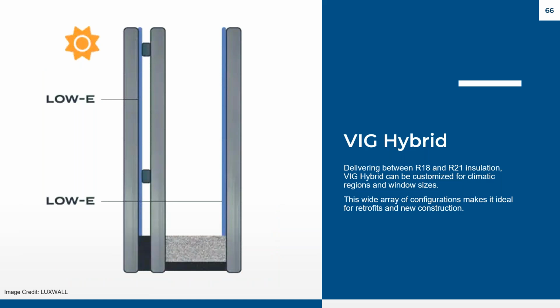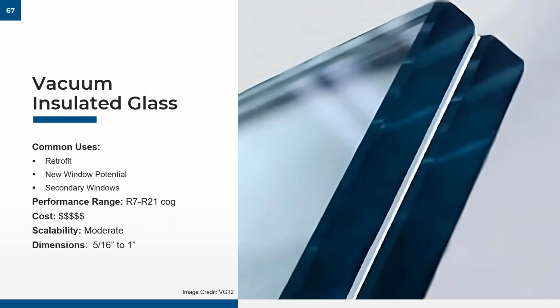In addition, vacuum insulated glass can be employed along with kind of more of a hybrid scenario. So you have your typical vacuum insulated glass on the left, and then that's married with an extra sheet of glass to create an extremely high performing glass assembly, like what you see here, ranging from an R18 to roughly an R21. Extremely high, especially if we're considering many of the dual pane systems top out about an R4 for comparison.